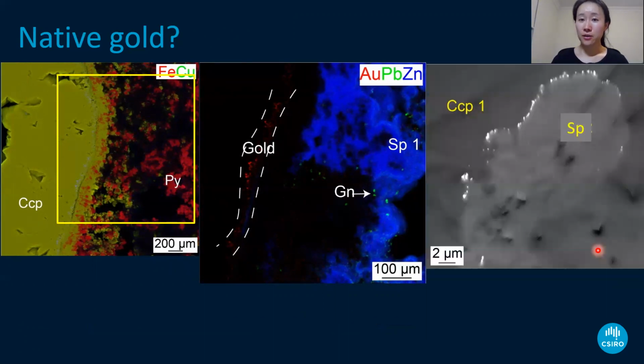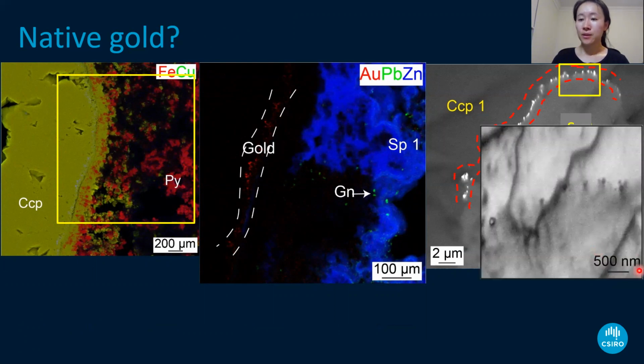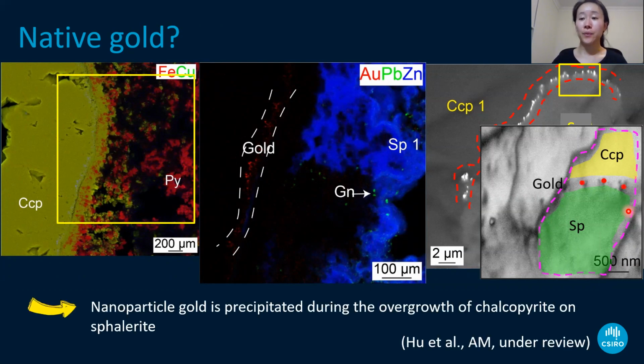If you look at the second one, very interesting. The gold only precipitates on the boundaries between the early sphalerite and the chalcopyrite layer here. We did EBSD analysis on this as well. We looked at a small area. It's very interesting. We found out that both chalcopyrite and sphalerite share one crystal. For example, here this is one crystal, but the top is copper-rich, indicating chalcopyrite, and the bottom is zinc-rich, indicating sphalerite. And the gold occurs as nanoparticles on the boundaries between them. We interpreted that the gold will precipitate due to the overgrowth of chalcopyrite on the sphalerite here.